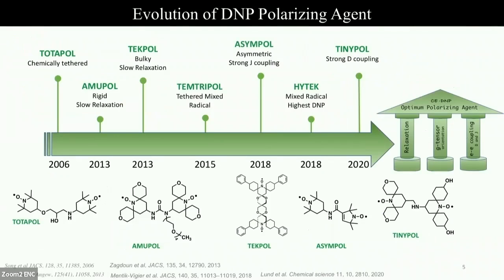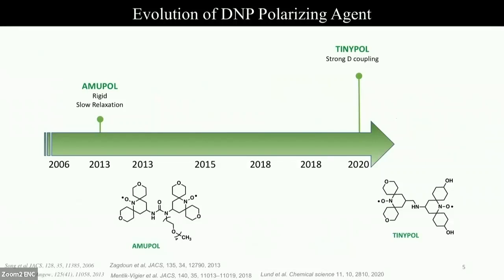In the last 10-15 years, a lot of different radicals have been synthesized, and along the process, we now have a better understanding of what spin parameters should lead to efficient cross effect DNP, such as the relaxation or G tensor. The one parameter that I'm going to focus on in this talk is the electron coupling network. As an example, I will take AMUPol and compare AMUPol and TinyPol, to show how the coupling should be tailored in order to have good DNP.